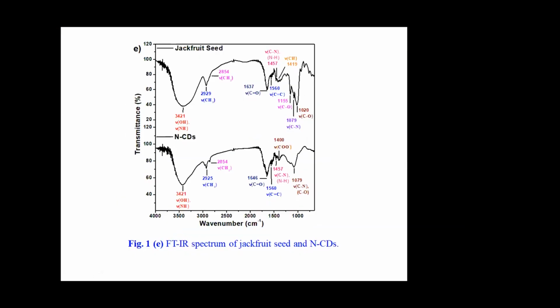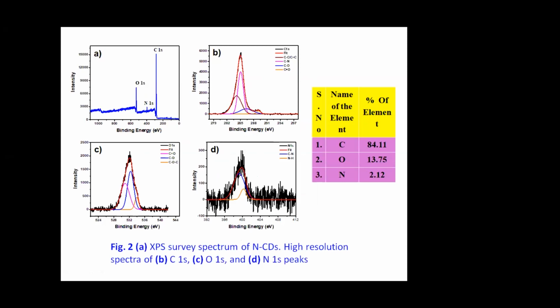Then we look at the functionalization of this carbon dot, comparing it with the raw material itself—the jackfruit seeds as raw material versus the quantum dots. We made a comparison of exactly how the functionalization occurs on this material, looking at the composition—carbon, oxygen, nitrogen analysis. We use XPS to make a thorough analysis of this material, which helps us find out the composition.